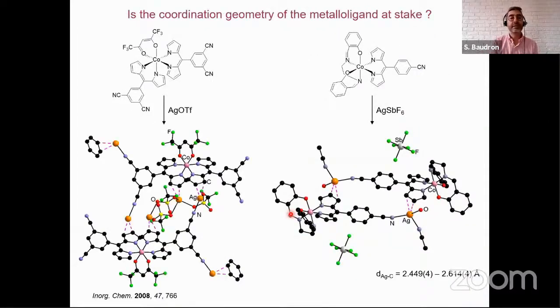So we went on to see whether this could be observed also with octahedral species. And this is indeed the case for those heteroleptic complexes. You can see here this complex with a cobalt hexafluoroacetylacetonate with two dipyrrins, or this cobalt salen with one dipyrrin. In both cases, assembly with silver salts showed the presence of silver-pi interaction, in this case in an eta 2 fashion for this coordination polymer, while with a cobalt salen compound, what we observed was a metallamacrocycle, where we have two cobalt complexes interacting with two silver 1 cations via silver-pi interaction, with a distance once again of 2.4 to 2.6, 2.65 angstroms.